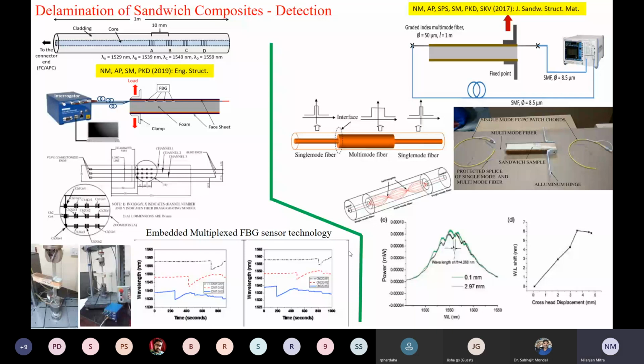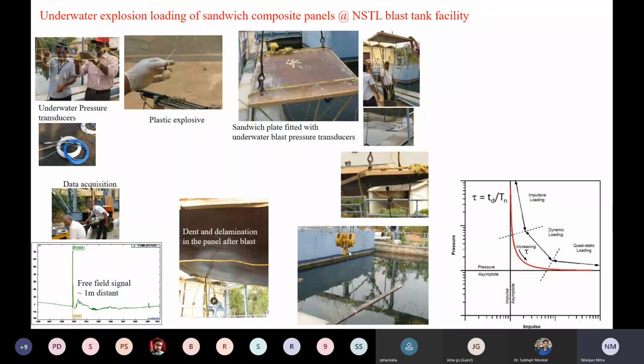Okay. We also carried out an underwater explosion test. This is at a facility at Visakhapatnam in NSTL, the Naval Science and Technology Laboratory in Visakhapatnam. We teamed up with them. We made big sandwich panels, glass fiber and then PVC foam, and we put them underwater, because our application was basically, as I said, Navy, submarine, those kinds of applications. As you see here, there's a small plastic explosive, a very small charge, not even 5 grams of TNT. We put it underneath the structure and let it explode underwater.